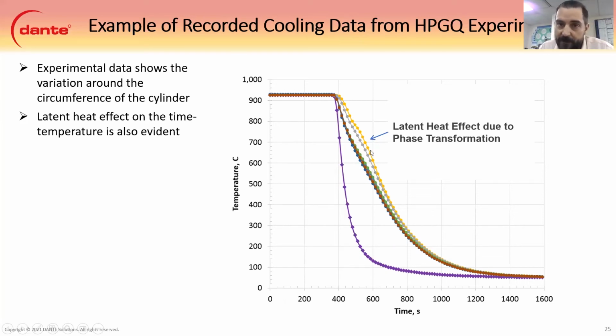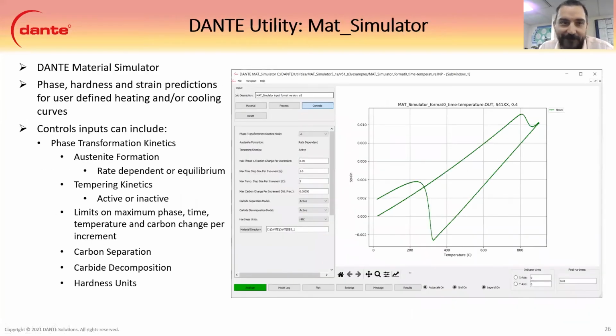And that latent heat is very telltale. We see that a lot. It's actually good stuff for us. So then the MatSim can also do, like I said earlier, temperature and strain. So you can do what we normally would see for dilatometry data. And we can use this as rate dependent for austenite formation. We have tempering kinetics, like I said. And then these are controls that limit the max amount of phase change per substep. And so this is something to give you better resolution as you get your plots done.